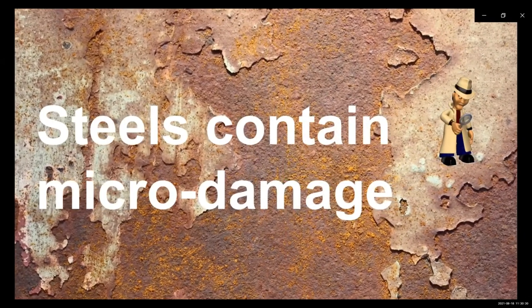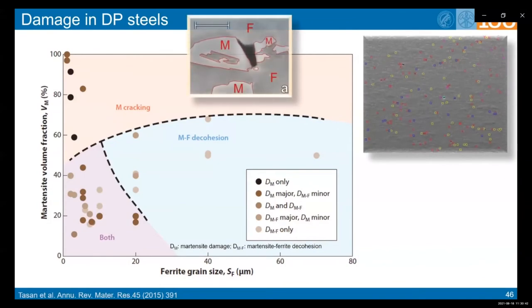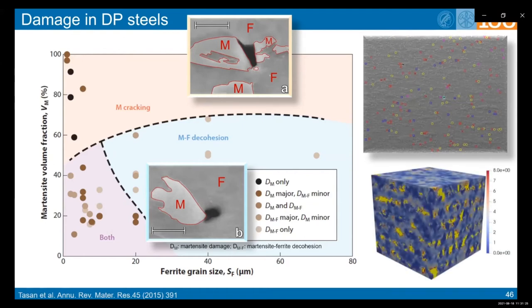Materials contain damage features, and damage simulation is becoming one of the main tasks for DAMASK in the coming years. A housekeeping analysis of delamination and fracture mechanisms in DP steels as a function of martensitic volume fraction and ferrite grain size — work from Stefan Zaefferer's team — shows cases where martensite breaks, apparently in conjunction with notch effects, and other cases with more classical delamination between soft ferrite and hard martensite. Scanning through microstructures reveals many such spots that should be included in corresponding simulations.